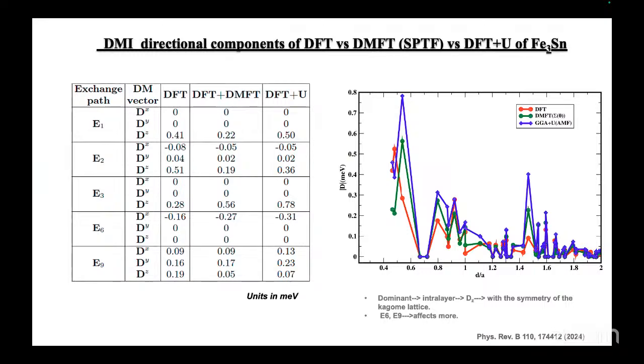But we get a lot of impact in the DMI interactions. When we include the DFT, DMFT and the DFT plus U, we can see it's strongly affected by the inclusion of this. And further analyzing the directional components of the DMIs, we can see that the DZ component is the dominating factor, which is in line with the Kagome lattices. This particular graph gives us an idea that DMI is quite affected by the external perturbations that we apply. And if in turn we introduce some kind of strain and doping, we can further modify our DMIs, and we can find many complex spin structures in the system. How will you get more complex spin structures here?